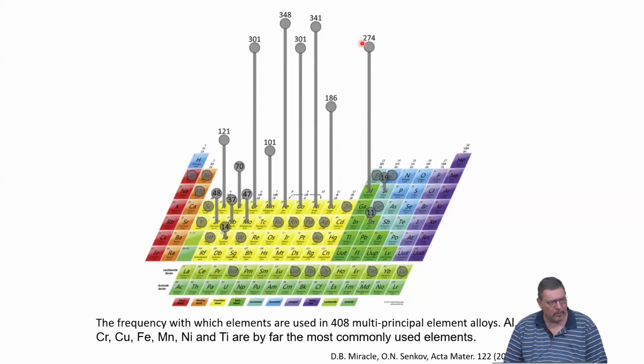This is very important if we later, in a few minutes, come to analyze which are the typical phases of solid solutions, because here you see that it's only a very small number of elements that are used heavily in making these alloys. And so it means that the structures these elements prefer, maybe you can expect that these will also control the phase formation in the high entropy systems that are made.